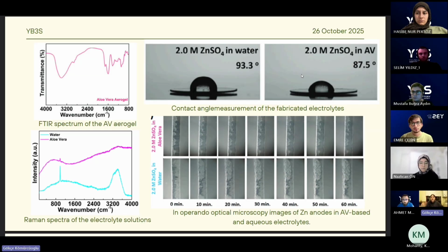In this contact angle measurement, we see that the angle is reduced with aloe vera. This means that aloe vera's wettability is much greater than the aqueous electrolytes. In this last picture, we see the microscopy image of a 1 hour cycle of the zinc anode in aloe vera based electrolyte and aqueous electrolyte. The zinc formation is much more regular in the aloe vera.